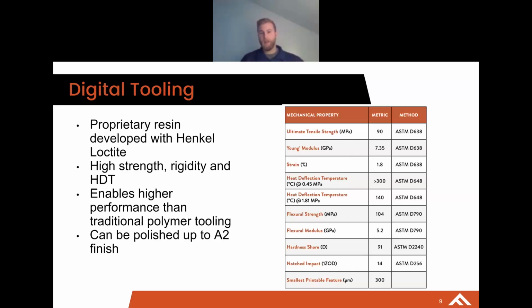As you guys can see here on our data sheet, we're at an HDT of somewhere over 300C. That 300C mark is right around 570, I think it's 572 Fahrenheit, which is about what we run polycarbonate at in the barrel. So the heat that the mold is actually seeing is probably a little bit less than that because we open our gates up pretty significantly to reduce shear heating. So while that mold is probably never going to get up to 300C, that's really the lowest benchmark that we needed to hit in order to get that increased performance.